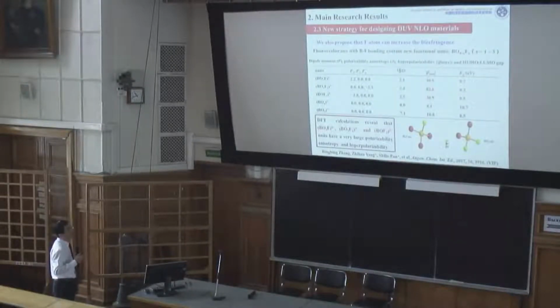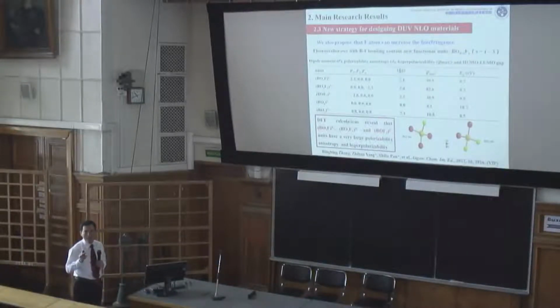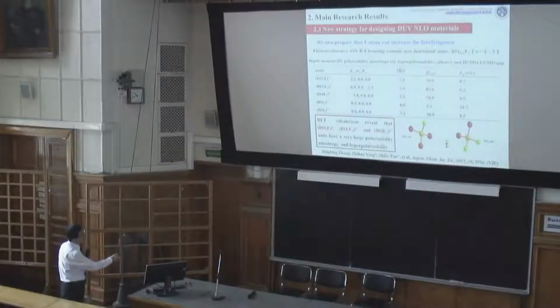And also, we want to get a material with large birefringence, because if the birefringence is large, it can produce the shortest UV laser wavelengths. For example, from this table, we use DFT calculation. We found that traditionally BO3 is a very excellent gene because it can produce a large SHG and a large band gap. After we substitute oxygen by fluorine, we can get these three units. These three units have very excellent properties. They can produce a large band gap, large birefringence, and large SHG. It means these kinds of units, these kinds of genes, may be the best candidates for designing new materials.